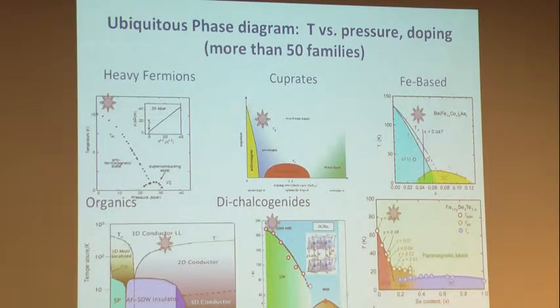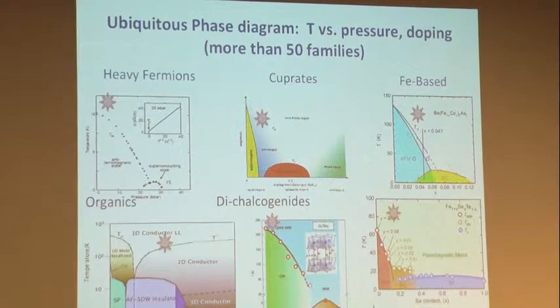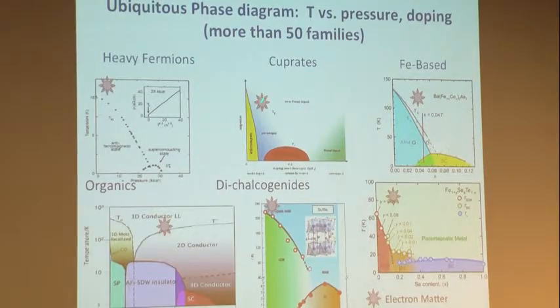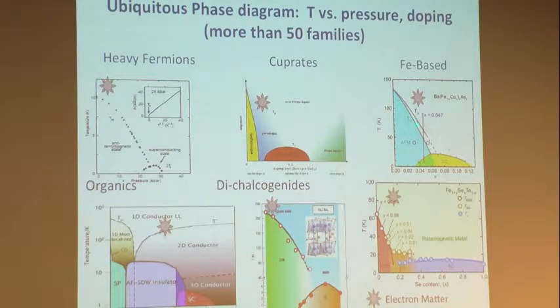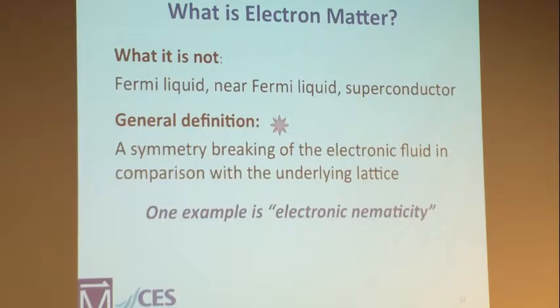Here's just a few. I could show you hundreds of these, but here's the cuprates, here's the dome, here's pseudogap, here's some iron-based, I'll show you some data we have from up here that shows the nematicity. These transition metal dichalcogenides are just cool. They have these charge density waves that have this changing charge density wave as a function of temperature. There's organics. Here's another. Anyhow, we can go on with that, but let me just go on. What is electron matter?